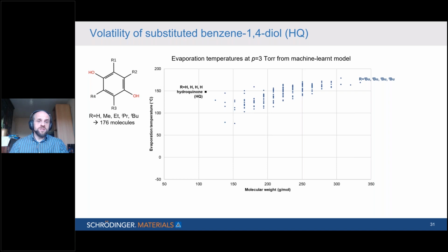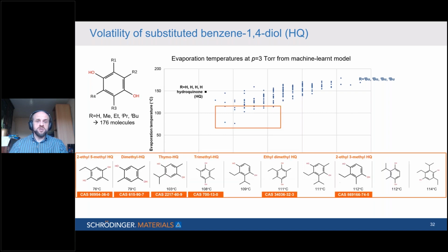And you can see hydroquinone on the far left. Obviously, it's the lightest of the set. And it has a predicted temperature of around 150 degrees C. Lots of the other molecules are actually more volatile, even though they have heavier, larger R groups attached to them. So let's have a look at the best ones, the ones that have the lowest evaporation temperatures. And I've listed them here on this slide.